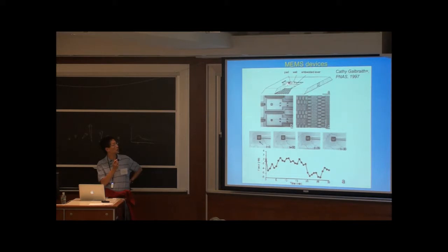So what he did was he made a pad that would sit up coplanar with the top surface of the substrate, and then have this long cantilever. You see that it goes underneath the substrate. So it's not on the surface. So the cell only sees this area and then that pad. But all of this stuff underneath is in a tunnel that's underneath the top surface.